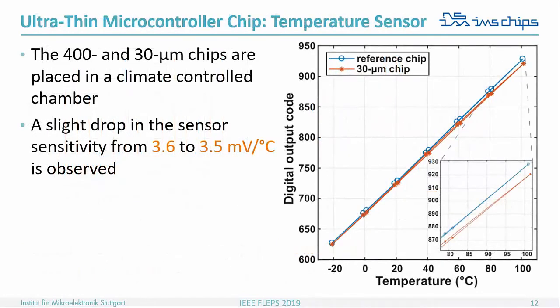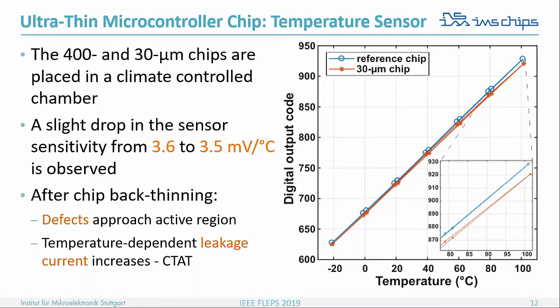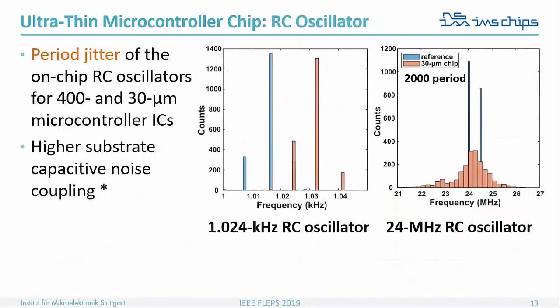The second test is that the integrated band gap reference on the microcontroller was tested in a climate chamber, and we can recognize that there is a slight drop in the slope, in the sensitivity, after thinning, and that could be due to the defects that can propagate after the back thinning to the active region. And these temperature-dependent leakages are CTAT, so it's complementary to absolute temperature, and that might be one reason for this slope degradation.